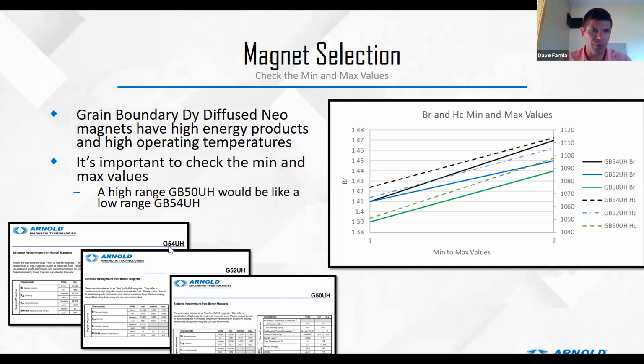And if we take a look at a range, so grain boundary diffused 54 UH, 52 UH, and 50 UH. All right, well, the 54 should be better. Should be stronger than the 50 UH. But if we plot those min to max values, so the solid line showing our remnant flux density at the minimum and at the maximum value from the data sheet, and the coercivity, the HC, minimum to maximum value, what we find is that GB50UH, if we're at the high end of our range for a GB50UH magnet, we're just above the low end of a GB54UH magnet. So it's really critical to understand what that range is, not just the nominal properties, but also what's the min and the max. If you get a batch of magnets, they could be at the low end of their tolerance. They're still to spec, but they could affect that performance in that end application.